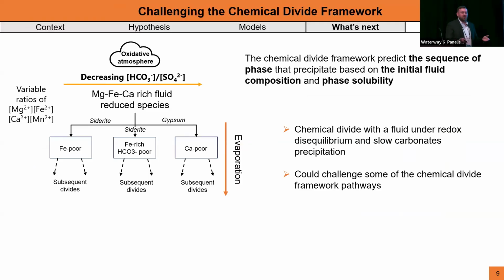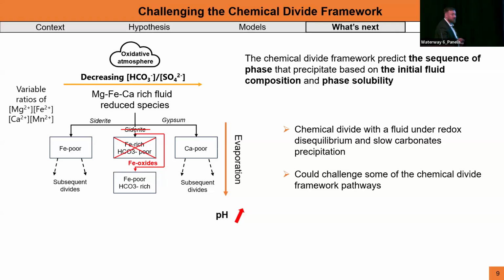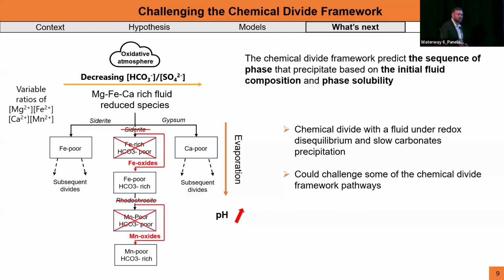Next up, why does this matter, right? So first, in terms of theory, it matters quite a lot because for those who do evaporation research, you know that evaporation in general is dictated by what we call the chemical divide framework. Basically, you can predict your sequence of evaporite minerals based on the initial composition of the fluid and the phase solubility. The issue is if you consider an initial redox disequilibrium, you could bypass such divides because as you evaporate, you raise the pH. So for example, instead of making siderite, you're going to start to make iron oxide faster than you make your siderite, and then it's going to change your chemical divide, and that could snowball, for example, with rhodochrosite, etc.